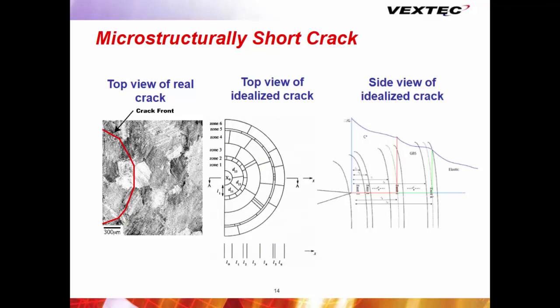So, just very, very quickly, I think it was talked about early, all of these models are based on what's going on in front of the crack, the crack tip opening displacement. So how much is that crack opening? What's your delta crack tip opening displacement? So closure comes into these models. Overload, if I get an overload, it's going to hold the crack down. So it's modeling the plasticity in front of the crack, and that plastic zone goes over multiple microstructural features. So it's the microstructure that exists in that plastic zone.